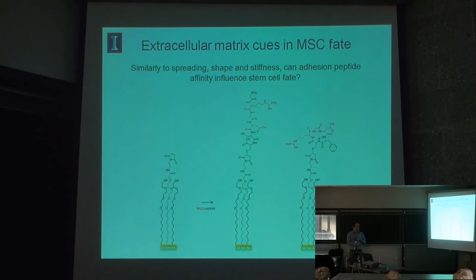And it's interesting because the difference between these is really just the conformation. And what this does is it's really a thermodynamics argument. So when the peptide is in this bent conformation, it'll slide right into the integrin binding pocket. Well, if it's this linear peptide, the protein has to do the work and fold it over. And so because of this, you get higher focal adhesion turnover as the cells are grabbing onto these cyclic peptides. You tend to get more focal adhesions throughout the cell and greater spread.